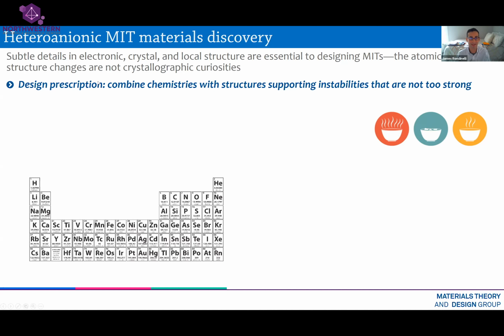And we need to do one other thing, which I haven't really explained to you, but we need to make sure that the structure isn't so strongly favoring, say, the monoclinic phase, the distorted one, versus the rutile one. Otherwise, we will always live in one state. So if you remember back, vanadium dioxide was able to transition from one structure to the other. The ideal one, where all the vanadium were equidistant, to the distorted one where some of the vanadium paired up. So the structure needs to be flexible enough to go back and forth.